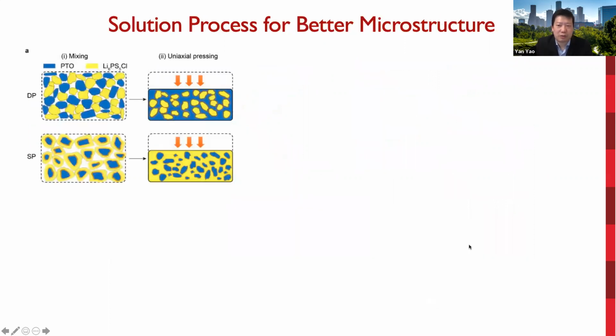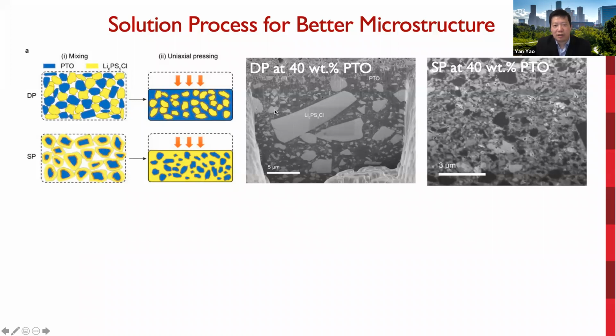So to reverse this microstructure, we actually invented a solution process method that preforms core-shell structure particles, where the PTO core is surrounded by the electrolyte shell. So the deformation of PTO during the uniaxial pressing process could change the microstructure compared to the dry process. The cross-section of the solution process composite at 40% active material shows that the phase separation is clearly reversed. Now the electrolyte domain forms a continuous network with the PTO domain embedded in between. This is in contrast with the dry process at the same PTO fraction.